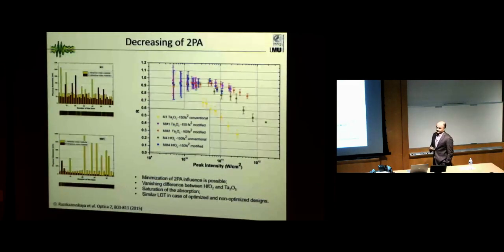It's a very interesting effect, but in the end, in the experiment we would like to have mirrors which don't have this effect or have a much smaller effect, and this can be solved by optimizing the electric field inside the multilayer structure. This is the original structure, which provides minus 150 femtoseconds squared delay, and it's shown on this graph with yellow dots, and this is the structure which we optimized for low two-photon absorption. It means the structure includes much more low refractive index material, because low refractive index material has a much larger band gap, and for low refractive index we don't have two-photon absorption, we need three-photon absorption, and of course it's a much less probable process. It means we significantly decrease the amount of high refractive index material, and of course it doesn't completely remove this effect, but it postpones it.